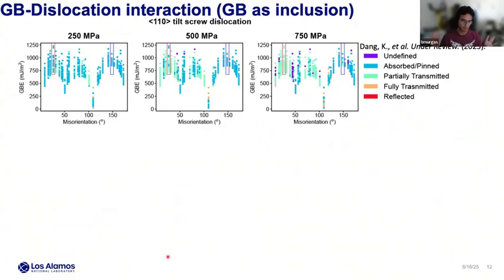In addition to the first slides where I showed you the grain boundary energy changes for the metastable states, we also computed this for the same structures. We computed the dislocation interaction, and for these cases my coworkers selected different types of grain boundary structures, and they changed the misorientation and also the normal. What they found is that depending on your misorientation, you can have different reactions, but also depending on whether you have a metastable or a stable state, you can have different reactions for the same grain boundary misorientation. And this obviously changes as you apply a higher stress.